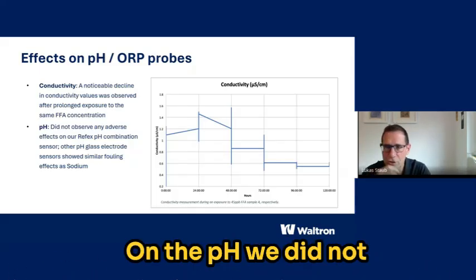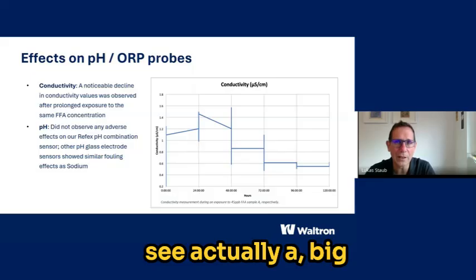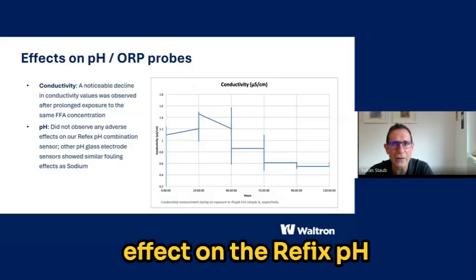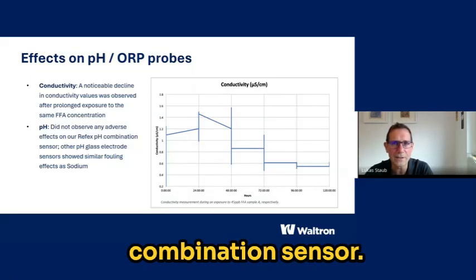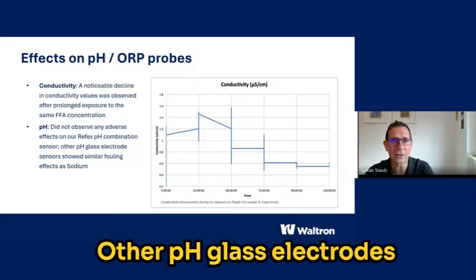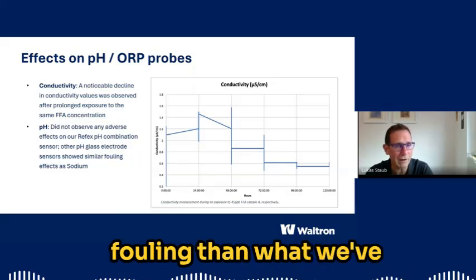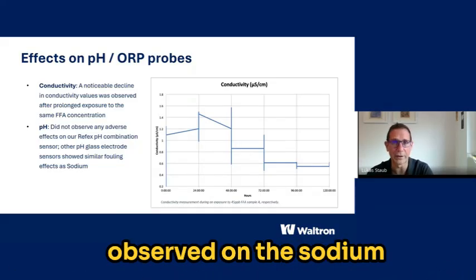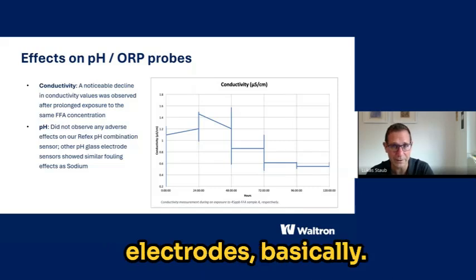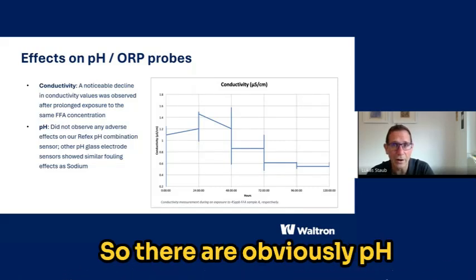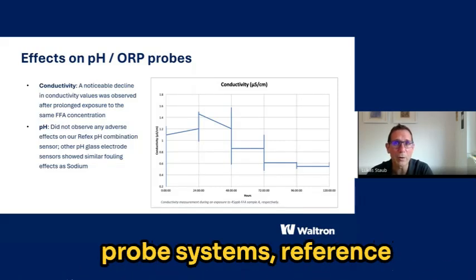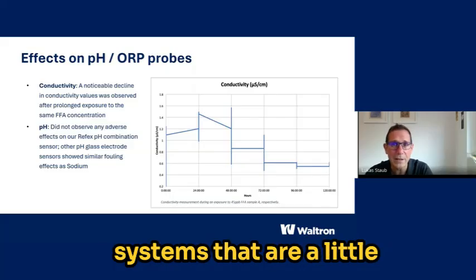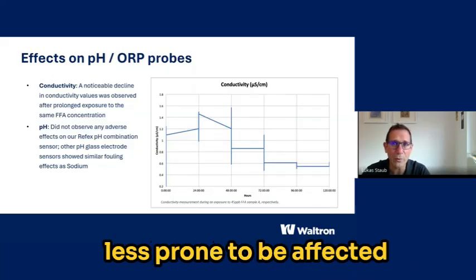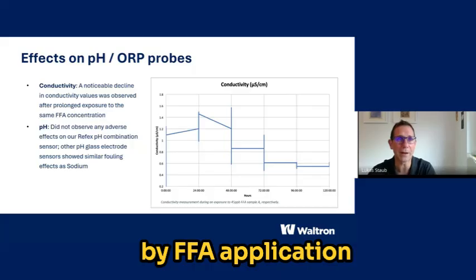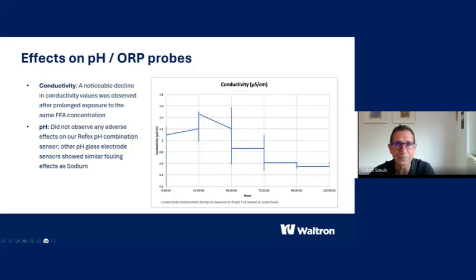On the pH, we did not see actually a big effect on the reflex pH combination sensor. Other pH glass electrodes showed very similar fouling to what we've observed on the sodium electrodes, basically. So there are obviously pH probe systems, reference systems, that are a little less prone to be affected by FFA application.